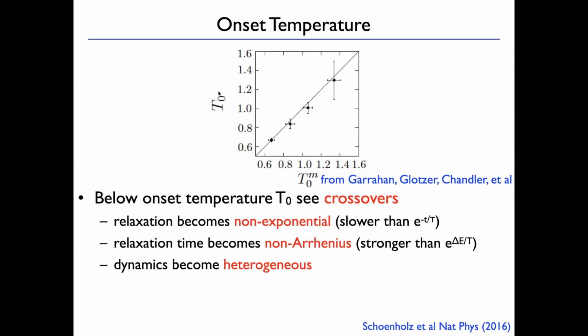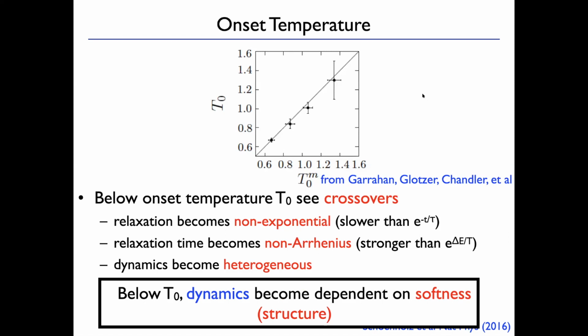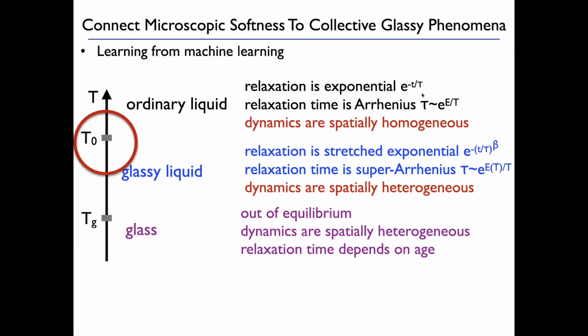And this is plotting our onset temperature versus the previously measured thing based on the phenomena, and they are the same. Okay, the dotted line is equality of the two. Okay, so we have predicted the onset temperature. That's a collective quantity. Okay, and it's below that the dynamics start to become dependent on softness. That's where the system becomes a glassy liquid instead of an ordinary liquid. All right, so that's what I've explained so far. Okay, that worked.